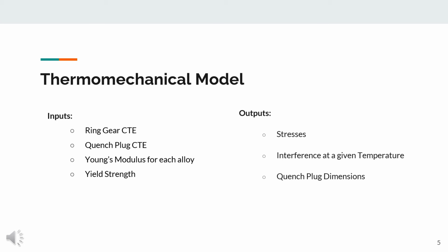The outputs gave us stresses. We took the summation of the tangential and diametral stress, made sure it did not exceed the yield strength or the critical buckling load at any temperature. We were also able to see interference at every temperature, which allowed us to adjust the design to make sure we didn't have any premature or excessive interference. Finally, the model gave us quench plug dimensions. This included the inner diameter, the outer diameter, and the thickness. We were also able to calculate the weight based on these dimensions.